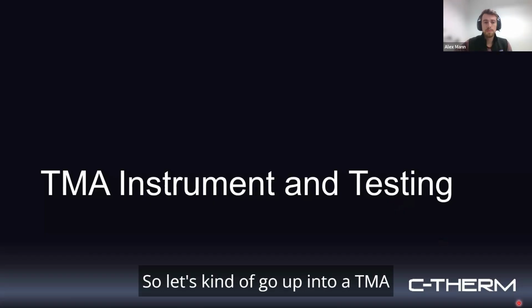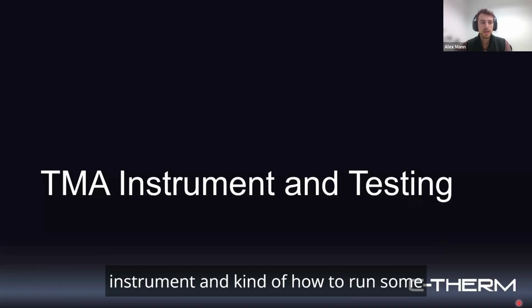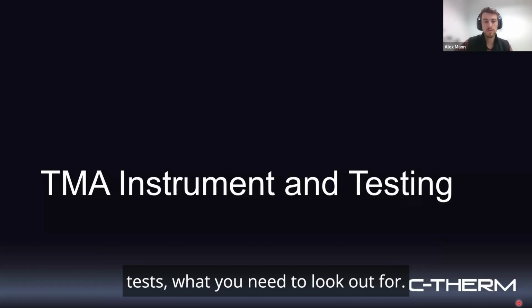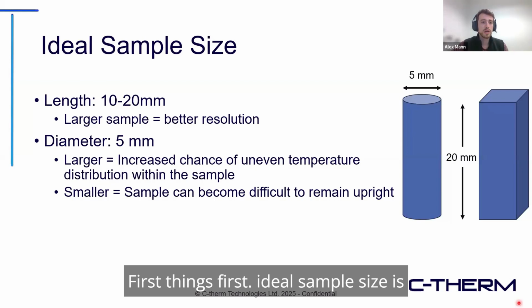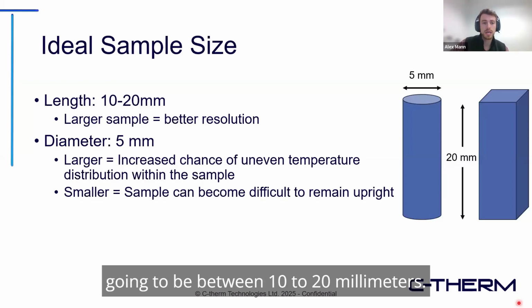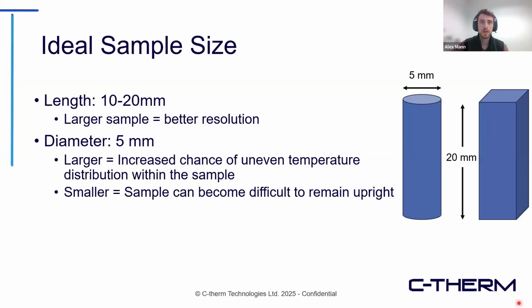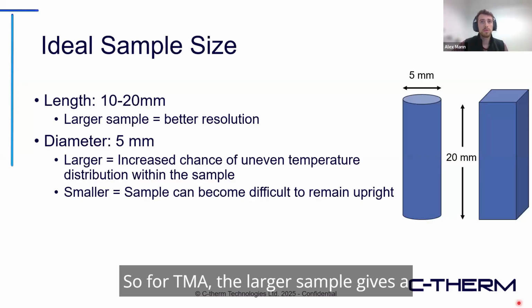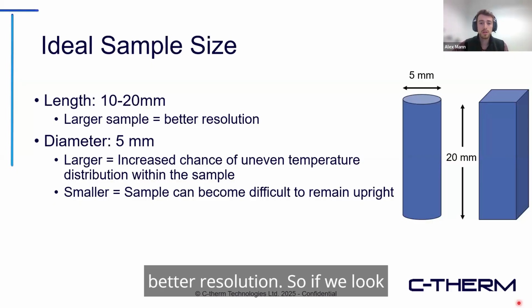So let's go up into the TMA instrument and look at how to run some tests and what you need to look out for. First things first, the ideal sample size is between 10 to 20 millimeters. For TMA, a larger sample gives a better resolution.